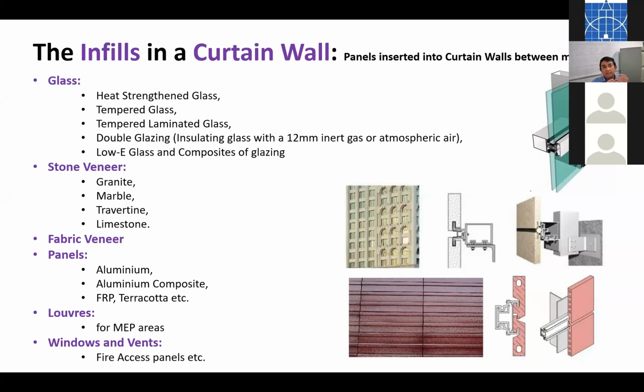Then in order to even prevent the crystals from flying around, we have tempered laminated glass, and the lamination is always done with an elastic membrane. Normally you use PVB, or polyvinyl butyral. The stronger one is called SGP. It's a trade name called SentryGlas Plus, but it is much stronger than the PVB, and also for areas where the laminated glass has to be exposed to weather conditions, water and heat and sunlight, always the prescribed type is SentryGlas laminated glass, because otherwise the PVB delaminates when it is exposed to weather elements for prolonged periods.